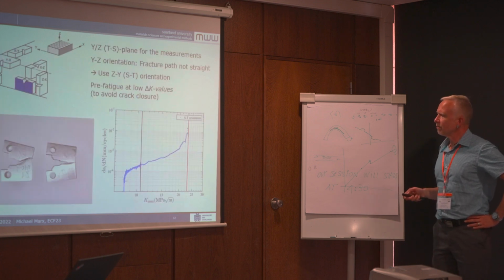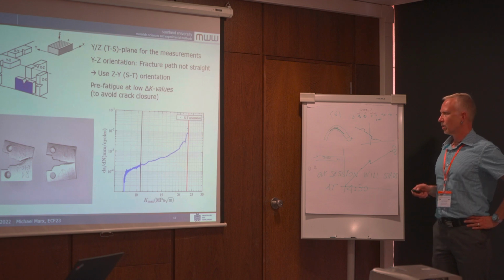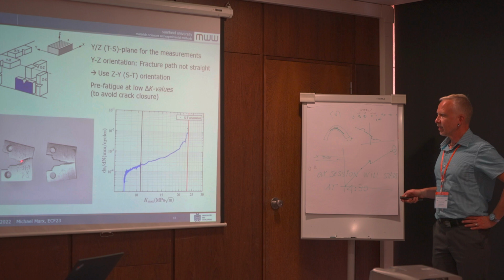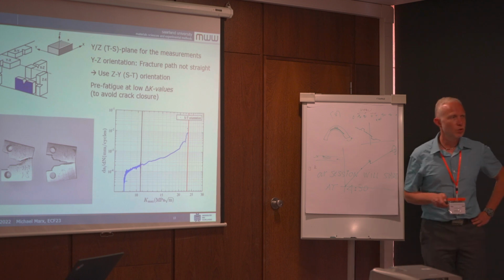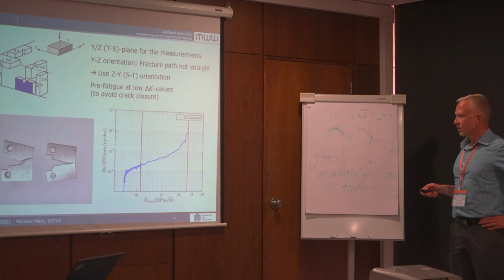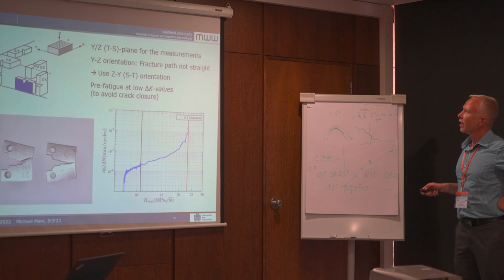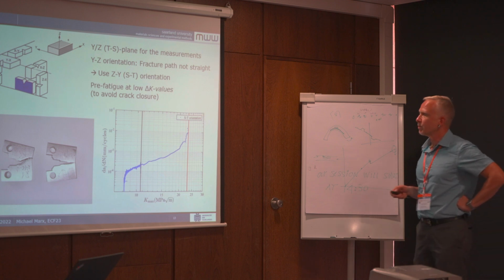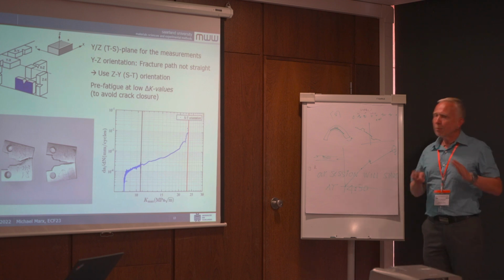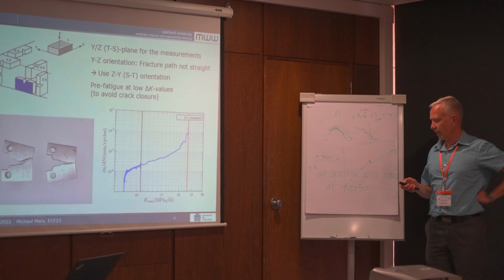What we also have seen, if we compare these two specimen orientations, is that in one case the crack is not growing straight, as we want it to have for a symmetrical stress distribution. Therefore, we selected the ZY direction here. In this case, this is our specimen plan. So these are some experimental details you have to keep in mind.